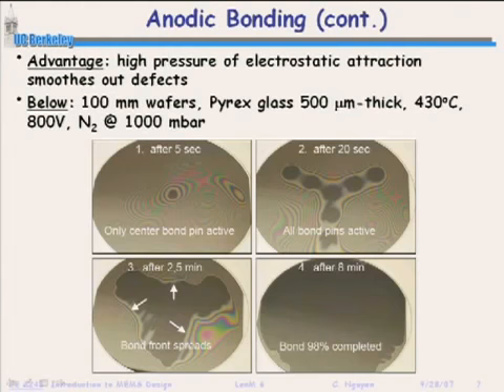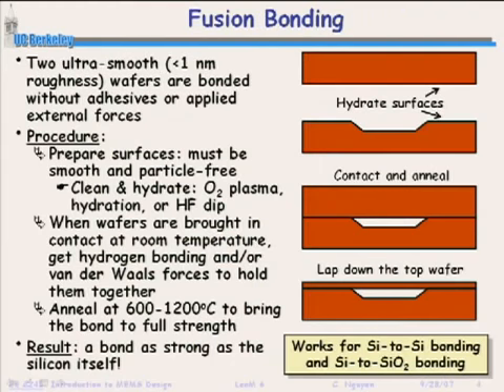It smooths out defects. Okay, so one of the big problems, I guess, with fusion bonding is this thing right here. You need ultra-smooth surfaces, right? Less than a nanometer of roughness. Okay, ultra-smooth surfaces also means that it needs to be extremely clean, because if you have a particle on the surface, right? If I was trying to bond two wafers together, say there's my wafer here, and two wafers bonded together. If I have just one particle right here, how much damage do you think that's going to do to this bonding? Quite a bit of damage, right? What's going to happen is you're going to have a ring or circle around that particle that's going to be not bonded. Okay, and maybe very small portions are actually bonded away from that particle.